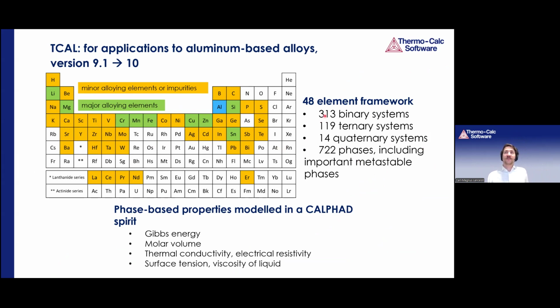There are over 300 binary systems assessed in this database, over 100 ternary systems, a couple of quaternary systems, and also over 700 phases described in this database. So for all of these phases, we have all of these properties described as a function of temperature and chemistry. And the properties are the Gibbs energy, molar volume, thermal conductivity, electrical resistivity, and the surface tension and viscosity of the liquid. We have not yet gotten to adding the elastic properties, but that's on the roadmap for the next update of the database, the elastic constants.